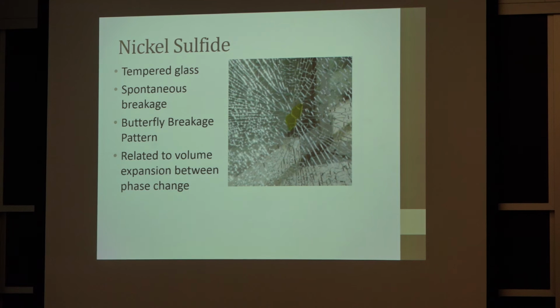If you've seen glass that has a nickel sulfide inclusion, it has this characteristic breakage pattern; they either call it a figure 8 or a butterfly type breakage pattern. And the reason nickel sulfide inclusion breakage is so scary is because it can happen spontaneously. You can have glass in service for 10 years and it can be fine, and then one day it just breaks.